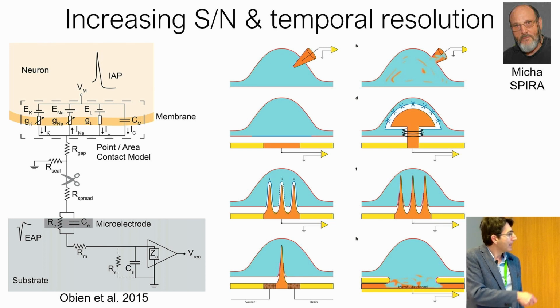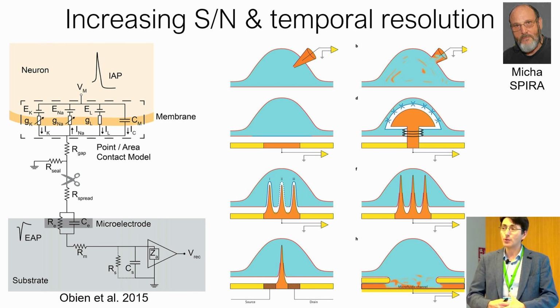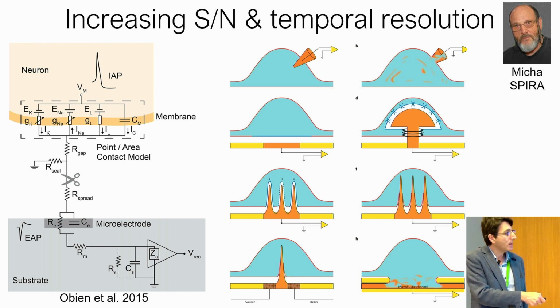And one idea, this is an electrical equivalent circuit model of the coupling between a neuron membrane and a microelectrode, is to make the seal resistance, which is a measure of how good is the coupling, proximity, or more accurately, the shunting to ground of signals, very high. This would make the signal-to-noise ratio much larger, which is what happens in a classic technique of whole-cell patch clamp, in which the seal between the pipette and the membrane is very high, in the gigaohm range.